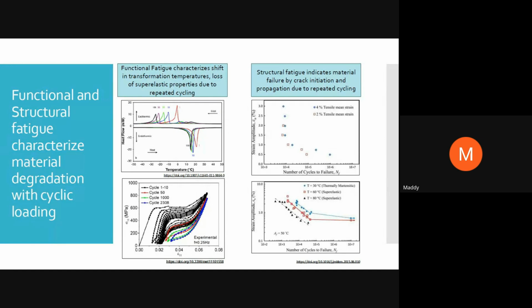Now, coming to the right-hand side, which is the structural fatigue, it's just like the fatigue in conventional material. So you are just looking at the failure of the material due to fatigue response from cracks, from inclusions, and you see how long of a fatigue cycle the material can survive. So if you see on the top, the testing was done at 4% tensile mean strain. And the one in the red hollow box is a 0.2% tensile mean strain.